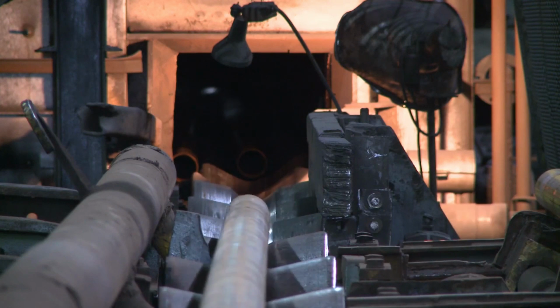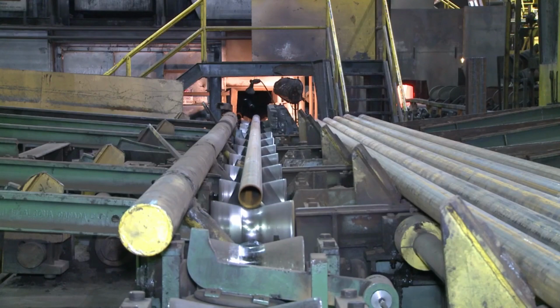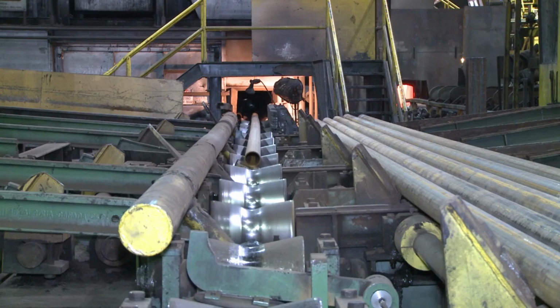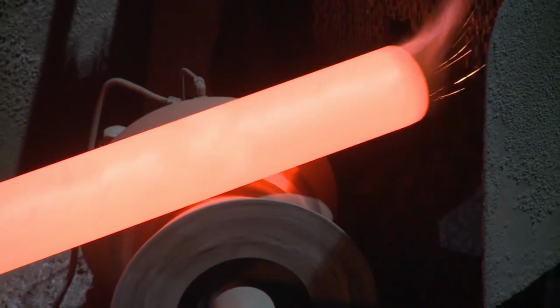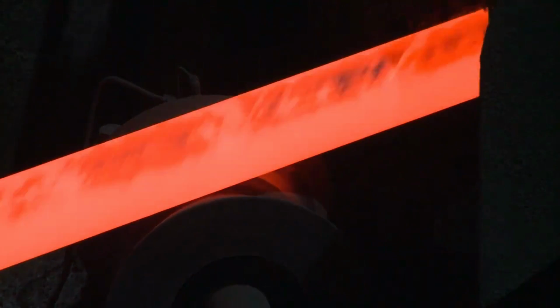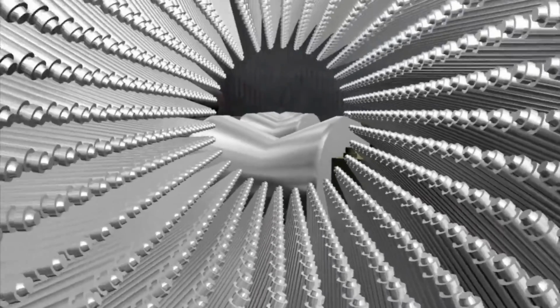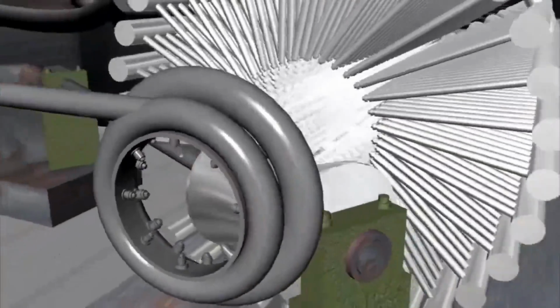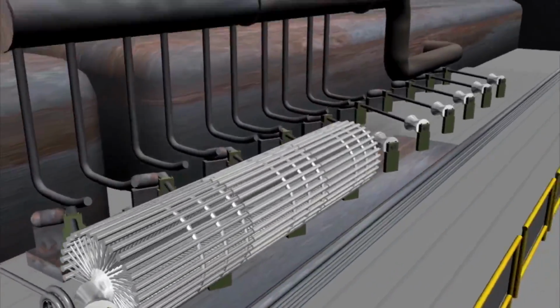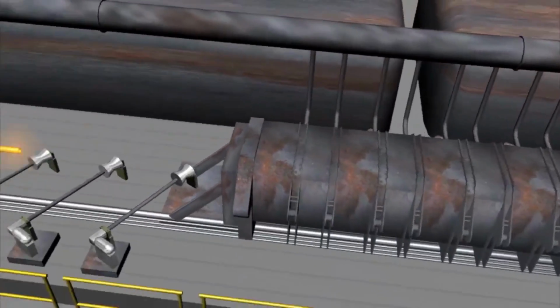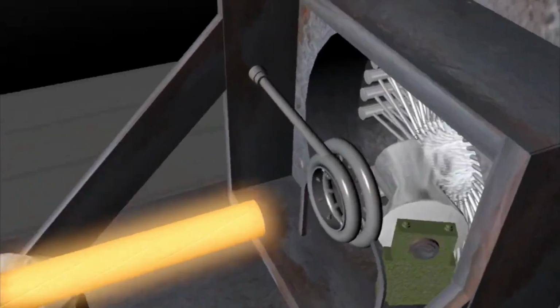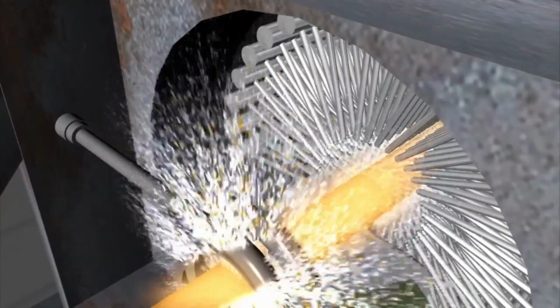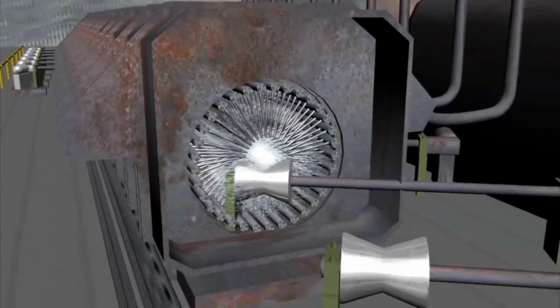The pipes are transferred and loaded into the walking beam preheat and quench furnace, where they are heated to 870 degrees Celsius. Once reheated, the pipes exit the furnace and pass through a water spray quench unit. The unit has 7 spray quench heads, each consisting of 800 individual water nozzles. Then, high-pressure water of the quench heads is evenly applied to the tube as it rotates through the machine.